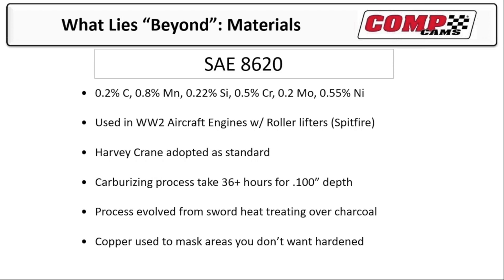8620 requires, to get 100 thousandths case depth, 36 hours to heat treat in the carburizing oven. So basically, this means all of our 8620 camshafts have to be run over the weekend. What happens is the guys load the oven on Friday, the last thing. They run it all day Saturday. It shuts down and cools off Sunday. Then they quench and temper it on Monday and send it to us. So when we're doing a run of 8620 camshafts, it has to be out of our business by about Wednesday, Thursday at the latest, and then it comes back to us on Tuesday the next week.